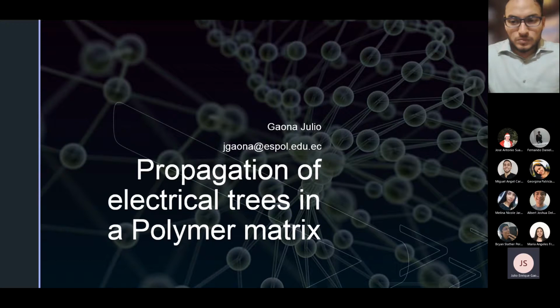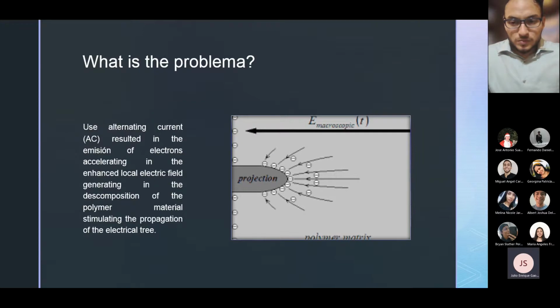My topic is the propagation of electrical trees in a polymer matrix. Okay, what's the problem in this case? A weak alternating current was passed through the decomposition channel of an electrical tree, and a small amount of alternating electrical quantity was present on the tip of the electrical tree, resulting in an intense local electrical field around the tip. The emission of electrons accelerated in the intense local electric fields resulted in the decomposition of the polymer materials.